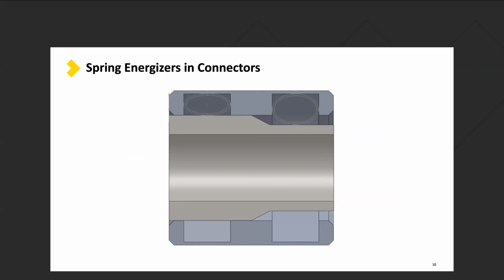Spring energizers in connectors. I do have one slide here just to touch on that to show the relative motion of the spring itself. Here we have a canted coil type spring. You see the profile here. When it's first installed, it's in what we call the free height. When it is compressed, you can see that it's squeezed radially in this case, both from top and bottom, and the spring is providing force outward and inward simultaneously to make that contact. It's different than a garter spring that just maybe pulls towards the ID. A canted coil spring pushes out in two directions to make sure the spring stays in contact.